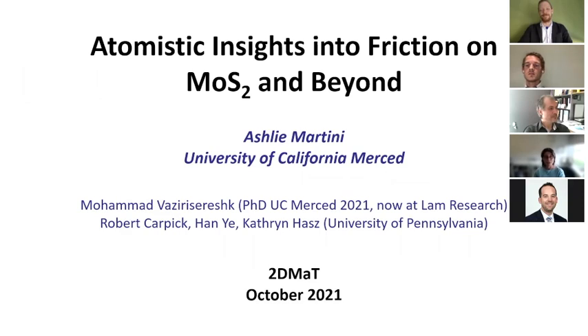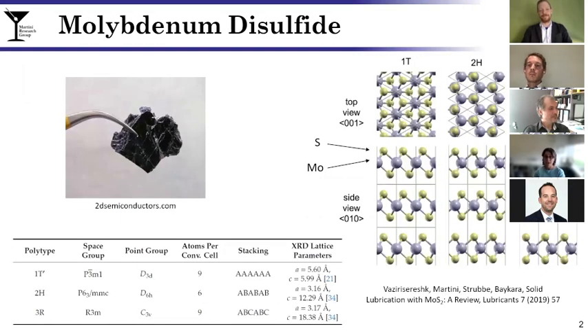So I'm starting off with molybdenum disulfide, or MoS2, and this is a layered structure comprising sandwiches of molybdenum and sulfur. As shown on the right, there are several different crystallographic phases that can be achieved both naturally as well as synthesized. They offer various material and electronic properties ranging from metallic to semiconducting. But from a tribological standpoint, which is my main focus, the key feature of MoS2 is the layered structure.